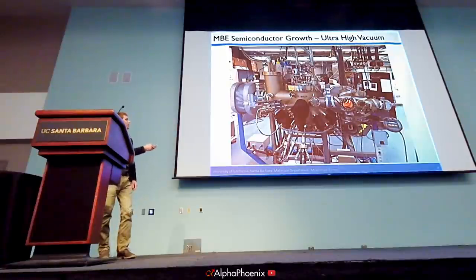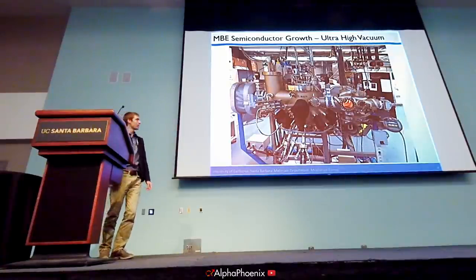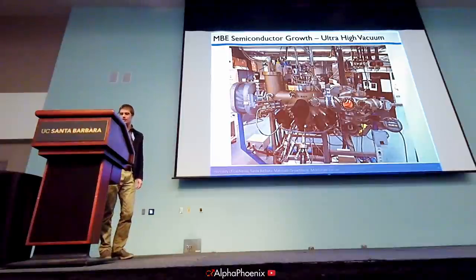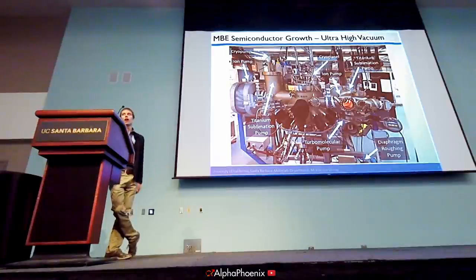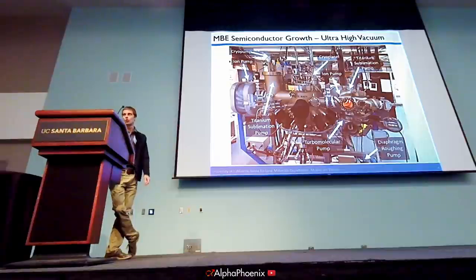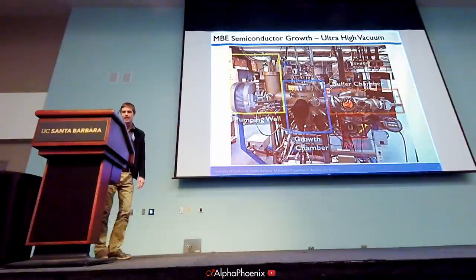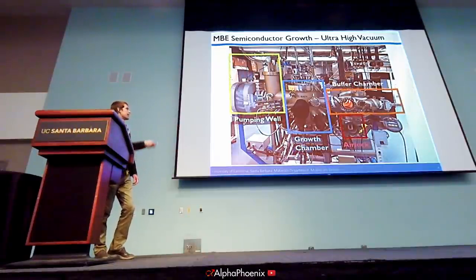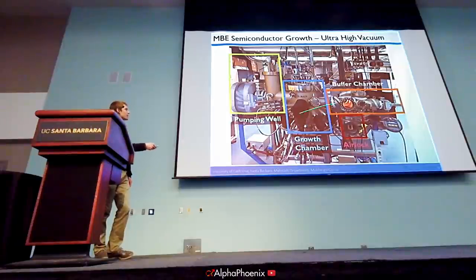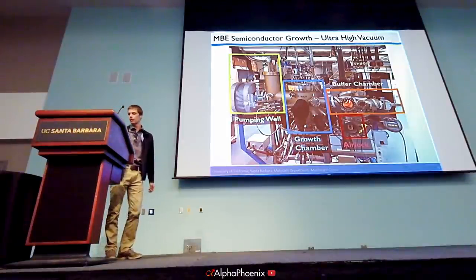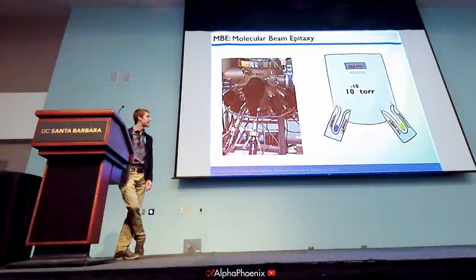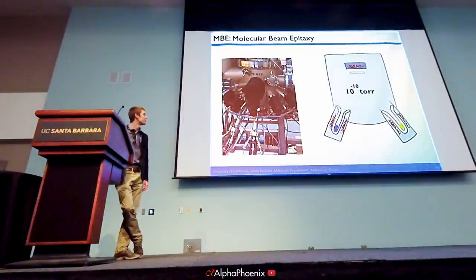MBE stands for molecular beam epitaxy. The first time I saw one of these systems I was a bit scared by it, because there's a lot going on — hoses, cables, a massive block of stainless steel. But honestly, most of it is just dedicated to pumping. There are seven different pumps on this system, because MBE growth is an ultra-high vacuum process — we run this chamber at around 10⁻¹⁰ Torr. For the purposes of understanding an MBE talk, you can really ignore all the pumping and transfer equipment and just focus on what's happening in the growth chamber.